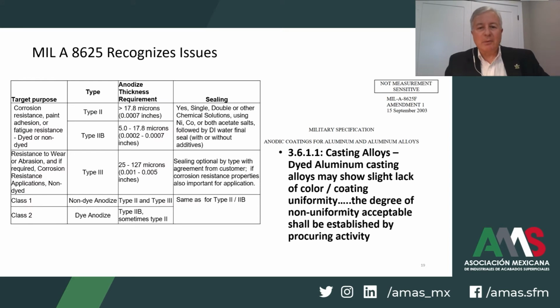Many anodizing applicators follow the military specification for applying anodic oxides on aluminum and alloys. The specification MIL-A-8625 recognizes that there are issues traditionally in trying to process cast alloys. In section 3.6.1.1, as it references cast alloys, it's stated that dyed aluminum castings may show slight variations and lack of color / coating uniformity. Well, the degree of non-uniformity acceptable shall be established by the procuring activity.